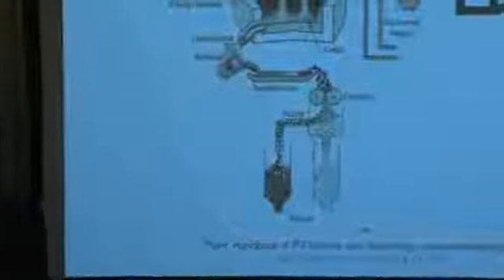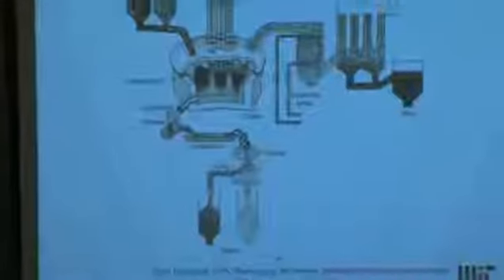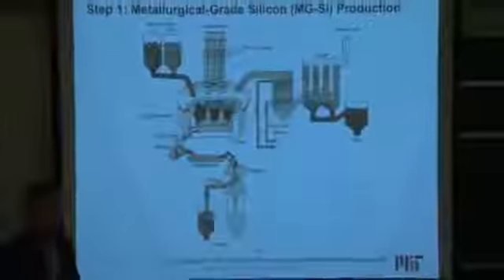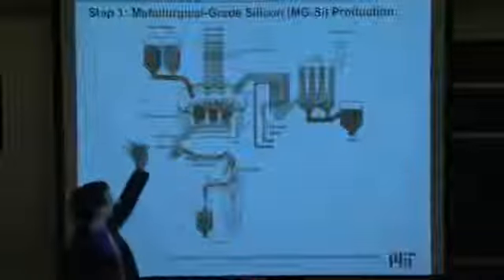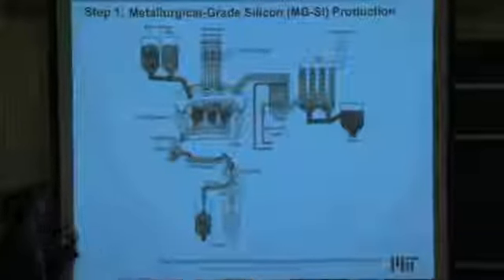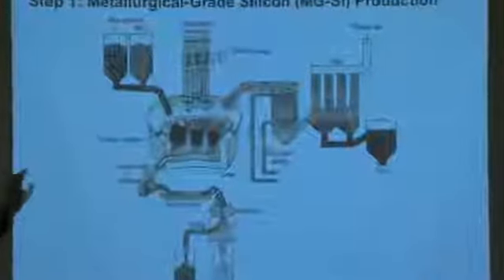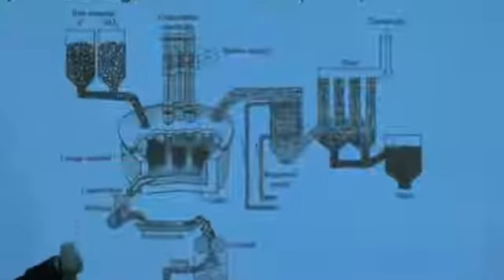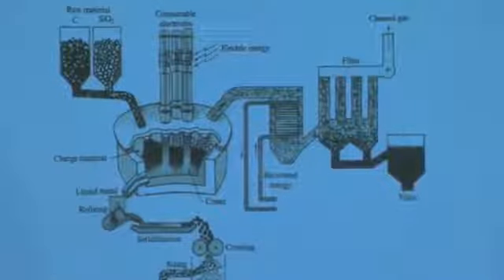It's very low resistivity because it has a very high impurity content still. The purity of this material coming out here is around 99.9% pure. So it sounds like a high purity, but if we're talking about parts per million of impurities, we have some further refining steps to do after this. So let's walk through this. We start with the raw materials in the upper left. It says raw material inputs, carbon and SiO2. The SiO2 form is usually quartz.